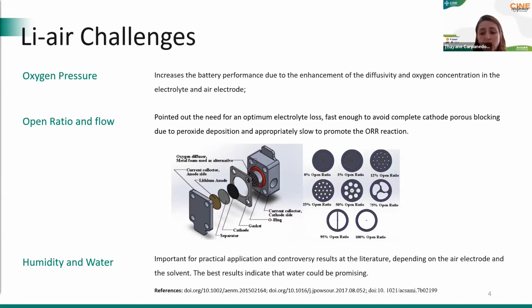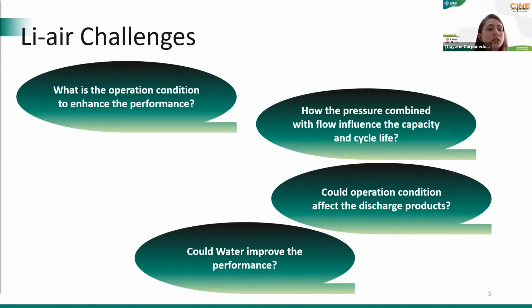And for practical application, the humidity in the air and the water in the electrolyte is an important point to be understood and solved. The literature presents some controversial results depending on the air electrode and the electrolyte, but the best results indicate that water could be promising for the battery's performance, especially when combined with catalysts, for example, ruthenium. But what's the operation condition to enhance the performance of the batteries, and how does the pressure combined with the flow influence the capacity and cycle life?